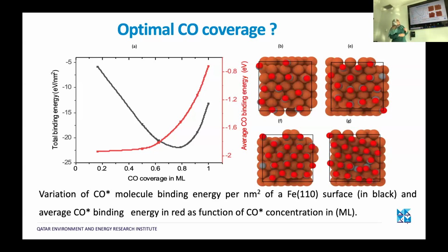So we conducted DFT calculations to look at how the total binding energy is correlated with the CO coverage in monolayers here, okay? And we found that the optimum between the average CO binding energy and the total binding energy is at 0.66 monolayers, which is approximately 2/3 monolayers. So this means that the most stable configuration would be that the surface is always covered by up to 2/3 monolayers of CO.